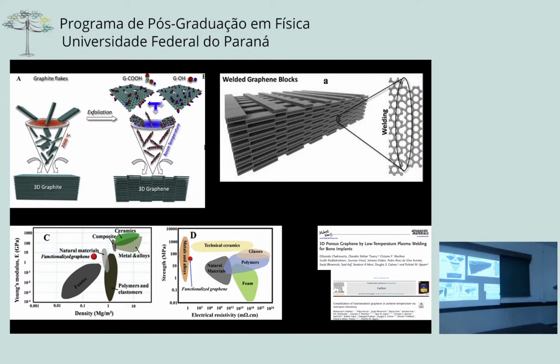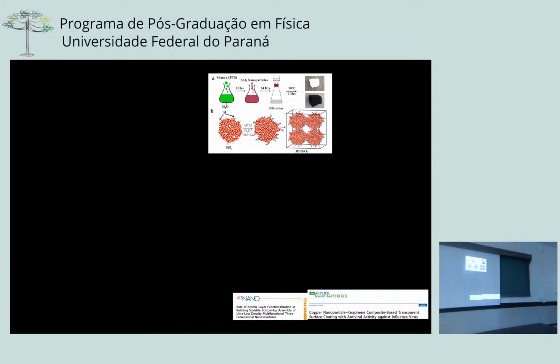Now graphene, they are as interconnected, they are fairly strong, the mechanical properties are better than most of the foam. Electrical conductivity is the same as metal. What it means is, the electrical contacts which you are making out of tin, copper and so on, you can make them light. So your phone can be much lighter, right? Not just that, they will have good strength as well. And it will be stable from liquid helium to 1100 degrees centigrade. It doesn't mean you are going to put your phone at that temperature, but the graphene if you make, you can do that, right? Having said that, graphene can be utilized to interconnect material as well.